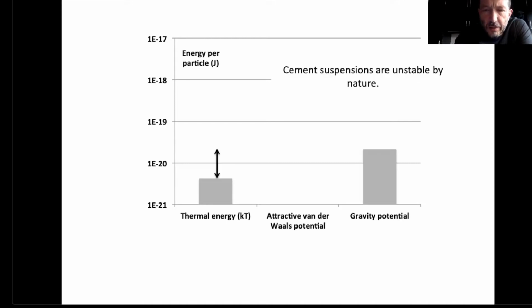So, first thing, gravity potential is systematically higher than thermal energy. This means that thermal energy is not able, through thermal agitation, to maintain the particles in suspension. So, as a consequence, cement suspensions are unstable by nature. So they do sediment, they do consolidate, and we expect these particles to be either too coarse or too heavy to be stable.